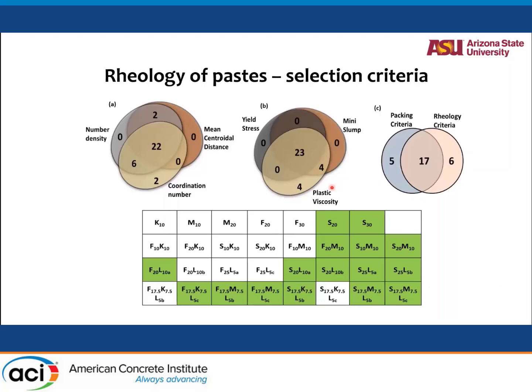So here is the selection criteria. This is from the packing criteria. Out of all the mixes, there were 22 mixes that satisfied the packing criteria. That was not surprising because we did not do trial and error. Even those 33 mixes were selected very carefully, so it was not surprising that 22 satisfied those. 23 satisfied the rheological criteria that we wanted. We could have been a little more rigid with the rheological criteria, weeding out a few more, but again, this was a methodology that we wanted to lay out that people can use based on how they find it efficient later on.